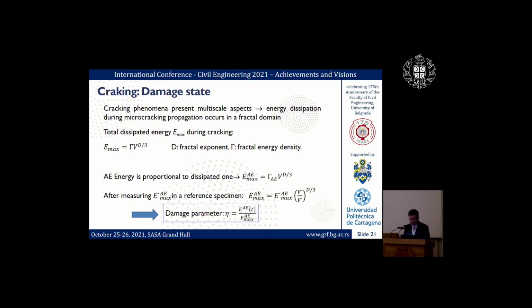This fractal dimension, as it is happening in a scale between a surface and a volume, has a value between 2 and 3, and it has been found that it tends to be the double of the parameter b that we have seen in the last slide. And as the dissipated energy follows this relationship, the acoustic emission energy that you are measuring, which is proportional to the dissipated one, is going to follow a similar relationship. This one is now called acoustic emission fractal density. And the important thing is how to relate it.